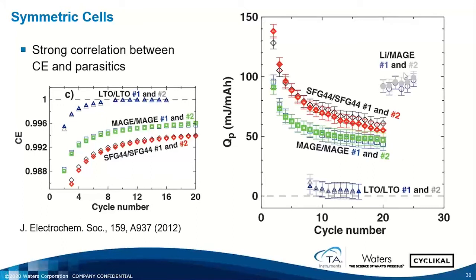I've also indicated here on the right the thermal data from a Mag-E half cell. So this cell here has metallic lithium in it, as well as Mag-E, the graphite. And you can see the contribution from metallic lithium, quite large in terms of its parasitics.